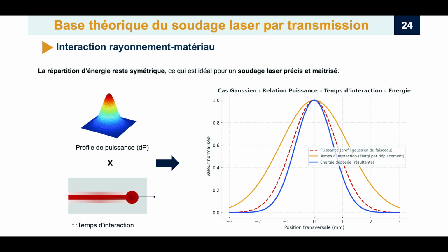Okay, now let's apply that moving Gaussian time factor to our standard beam profiles and see why they fail for these narrow window materials. First, the standard Gaussian power profile. Right, so you start with a Gaussian power profile, P, which is already intensely peaked in the center. And you multiply that by a Gaussian time profile, T, which is also peaked in the center because of the movement. What happens when you multiply two functions that both peak strongly in the middle? The result is extremely peaked in the middle. The deposited energy, E, is massively concentrated right at the center of the weld track. Exactly. That super intense central energy peak easily blows right past the degradation temperature, TD. You get immediate burning, charring, maybe even that keyhole effect we talked about. Instant material damage in the center.